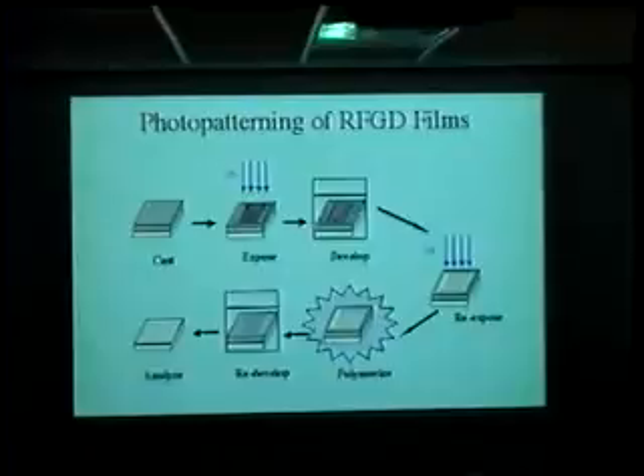We've also learned to take this coating and use lithographic methods to photo pattern it. I'm not going to go through the steps, but it's a pretty conventional photolithographic process to make patterns. And in some recent work with Carl Boehringer, who's a professor in our electrical engineering department, and two postdocs in our group, we patterned this glyme. And you can't really see anything. Again, the film's 20 nanometers thick, so there's nothing to see on the surface. But we've indicated with these dotted lines where we patterned it. Everything inside the dotted lines, we have removed the glyme, so it's bare glass.